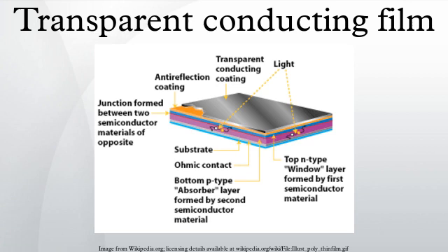To enhance their electrical properties, ITO films and other transparent conducting oxides are grown in reducing environments, which encourage oxygen vacancy formation. Doping and ionization within the oxide occurs in the same way as in other semiconductor crystals. Shallow donors near the conduction band allow electrons to be thermally excited into the conduction band, while acceptors near the valence band allow electrons to jump from the valence band to the acceptor level, populating the valence band with holes. Carrier scattering in these oxides arises primarily from ionized impurity scattering.